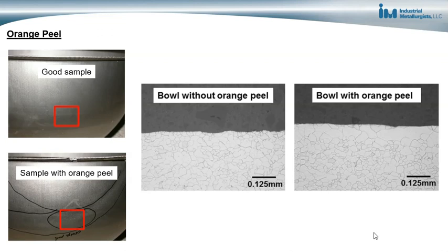The steel manufacturer had to put measures in place to prevent the cooling problems. Additionally, my client did not have anything in their specification about maximum grain size. We evaluated steel from different lots of material and determined the maximum grain size that could be tolerated before orange peel would occur, and put that into the specification. With that, the problem was eliminated and orange peel did not occur after that.